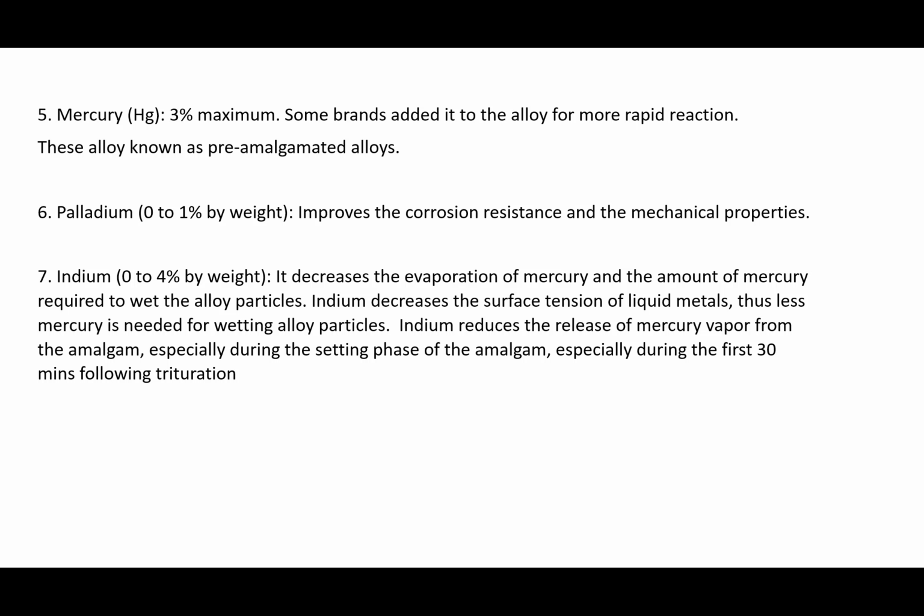Palladium is to improve mechanical properties and improve the corrosion resistance. Indium is to decrease the evaporation of the mercury. Actually, indium reduces the release of mercury vapor from the amalgam, especially during the first 30 minutes following trituration. So this is all about the composition of the amalgam.